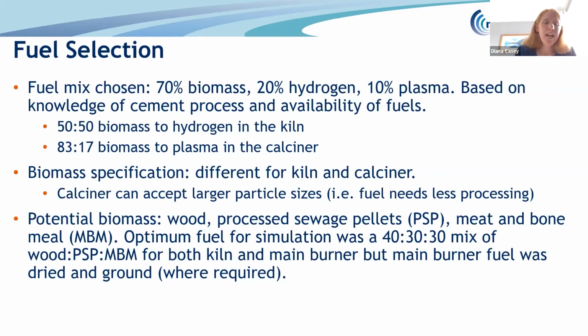So in terms of fuel selection, the project team used experience of the manufacturing process, along with the knowledge of fuel availability, to propose a fuel mix of 70% biomass, 20% hydrogen and 10% plasma. So plasma energy is a complete unknown for cement manufacture, and therefore presents a more challenging technology. So as a result, it was selected to contribute a smaller fraction of the heat required, particularly in the calciner, and several different options for its use were proposed.